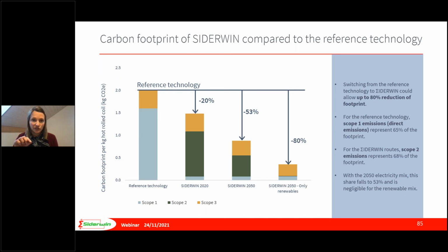Secondly, we can see a switch in the scopes that contribute to the carbon footprint. So we have this switch from scope 1 to scope 2. For the reference technology, scope 1 emissions, so direct emissions, represent 65% of the footprint. And for the Siderwin route in 2020, scope 2 emissions would represent 68% of the footprint. Then we can see in the two 2050 scenarios that this share of scope 2 emissions can fall down to 53% and even be negligible in the case we would have a purely renewable electricity mix. So finally, we can see the influence of the electricity mix and how this is key to ensure the decarbonization potential of the Siderwin technology.